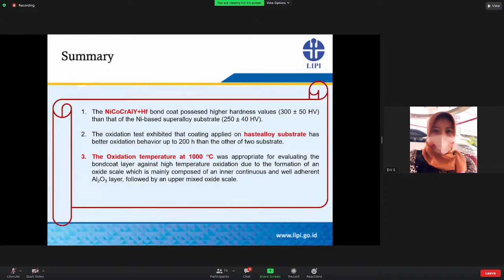high temperature oxidation. Based on the summary, and to confirm the previous result for the bond coat layer, a further coating was also prepared with hafnium additions and compared with another reactive element, cerium, as can be explained in this slide.